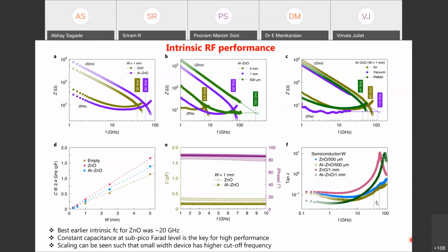So this slide shows the intrinsic cutoff frequency, or the RF performance, of the diode. As you can see here, impedance is plotted as a function of frequency, and the bottom is the real part, and the slanted line is the imaginary part. For zinc oxide and aluminum doped zinc oxide, as I told you in the previous slide, we can expect a little bit better performance from AZO. As you can see here, the cutoff frequency for zinc oxide was 38 gigahertz, while for AZO it is 60 gigahertz. Okay, so this is a significant improvement.